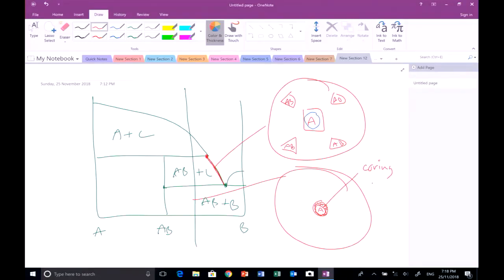Oh my God. And then we knew from other studies that the thing was heavily contaminated by boron. And B2O3 has a much lower refractive index than the matrix. And I said, well, that'll drop the refractive index, but that doesn't explain why it goes down, because when we heat it up more, this boron evaporates very readily. So if I reduce the boron, I've got a composite, and the refractive index of this composite will drop because of the mixture of the high and the low refractive indices. But if I'm removing the low, it should rise again. So the recrystallization and the exit of the boron both should raise the refractive index, and it dropped.